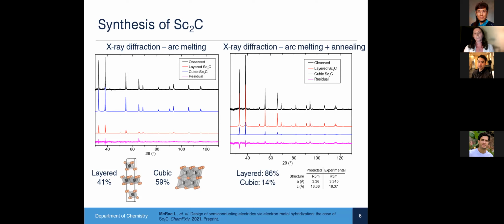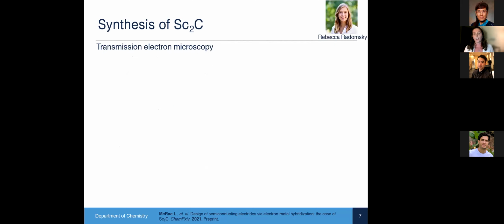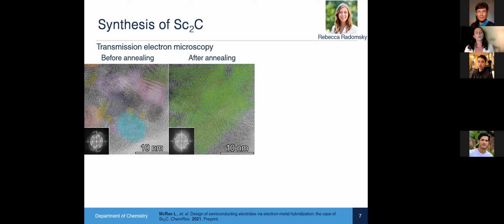We wanted to explore the effects of annealing a little bit more in depth. So we used transmission electron microscopy, and my colleague Becca Radomski took many of these images. Before annealing and after annealing, we could see that there were much larger crystal domains after we annealed. So here I'm showing TEM images that have color coordinated crystal domains.